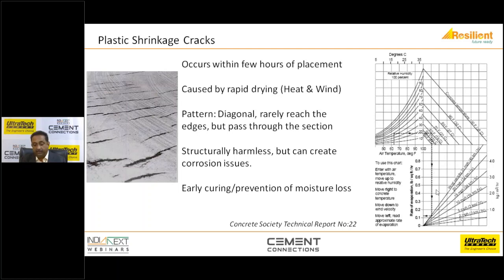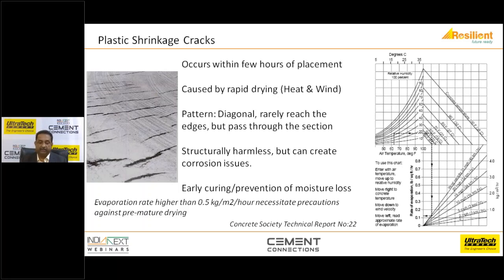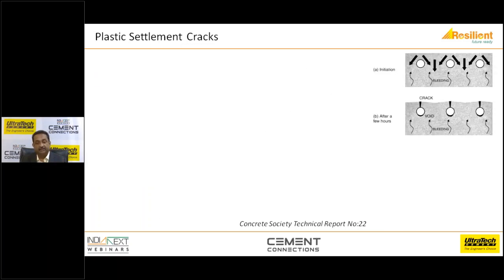From there, you come down to this particular graph, which is your wind speed. And then when you plot it back to your y-axis, you will get the rate of evaporation. So if your rate of evaporation is less than 0.5 kg per meter square per hour, then you are okay. If it is exceeding 0.5 kg per meter square per hour, then you need to take precautions. The second one is the plastic settlement cracks.